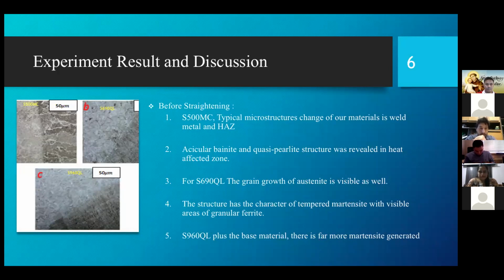For the first one, the S500MC, we observed a typical microstructure change in the heat affected zone, and also some acicular bainite and quasi-pearlite structure in the same zone. For the second material, the S690QL, the same deformation was observed, plus some grain growth of austenite and visible bainite also. For the last material it is the same, microstructure change plus some more martensite generated in the heat affected zone.